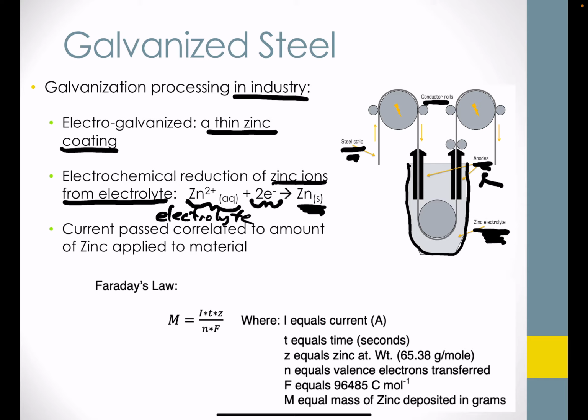Anodes here are typically zinc solid to restore any zinc ion that is lost in the process. Okay, so here's our zinc 2+ aqueous that we saw a moment ago, and that is going to be applied to the steel strip as it passes into this electrolyte bath. After some time in the bath, of course, if this were a continuous process, that steel strip is removed and passed outward as product for clipping or cutting to produce the freestanding product.